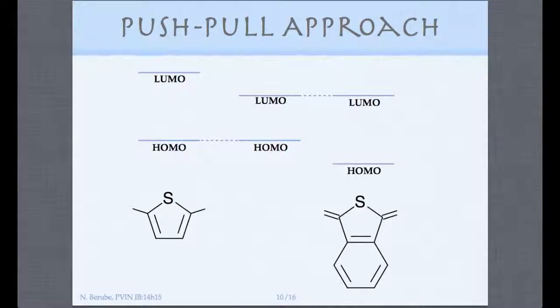Yay. Now my approach says that no, you mix an aromatic one and a quinoid one, and they will mix into this copolymer, which will be in between aromatic and quinoid, which will lower the band gap. Now this model doesn't say anything about the precise place of the HOMO and LUMO level, because this depends on, for example, if you use nitrogen or oxygen or all those other handy add-ons that we pushed aside at the beginning of this talk.